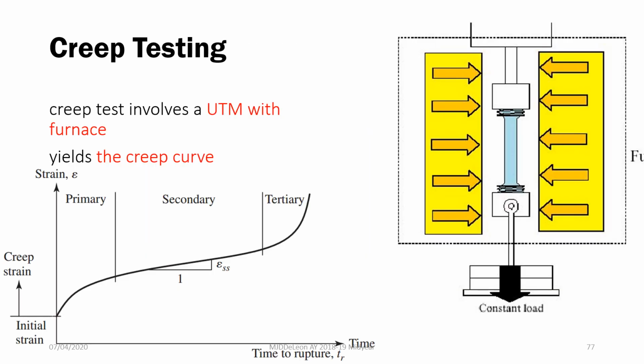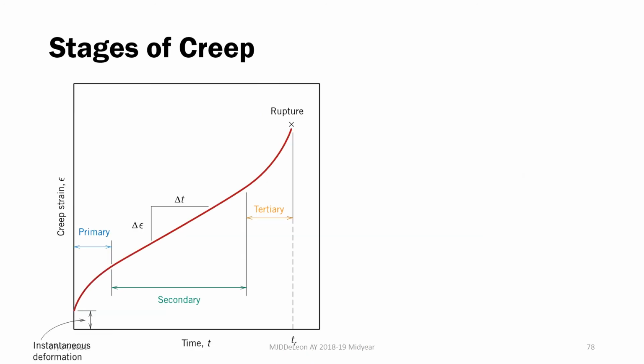So to test our materials for creep, we usually use a UTM or a universal testing machine under a furnace or at an elevated temperature. So this yields us our creep curve. So in this case, ang ginagawa natin is we're holding our material at a constant stress and measure natin yung strain natin with respect to time at an elevated temperature. So from the creep curve, we can see different stages of creep. You have your primary, secondary, and tertiary stages.